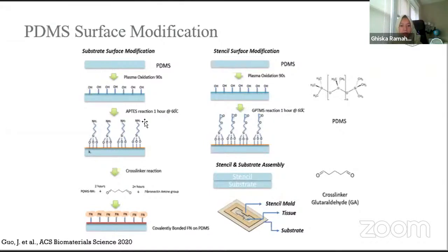And then by doing some other cross-linkage by glutaraldehyde, this PDMS with NH2 group can be covalently bonded with fibronectin. So what is fibronectin? Fibronectin is basically a protein that can bind to your cells. So once we get the fibronectin onto the PDMS, the cells can attach to our PDMS. So then we can mechanically couple the cells with our PDMS substrate. Okay, and then we have our stem cells on top of the substrate as well.